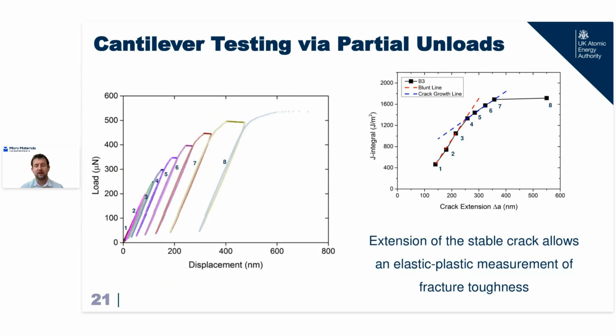brittle behavior. It's plastic enough that we have to use the J integral and an elastic plastic measure of fracture toughness to evaluate it. By using these load partial unload tests, where the load is gradually ramped up and reduced, you can track through that stable crack growth, crack extension, the changing compliance of your cantilever. You can build up this crack growth line and therefore evaluate this elastic plastic fracture toughness.